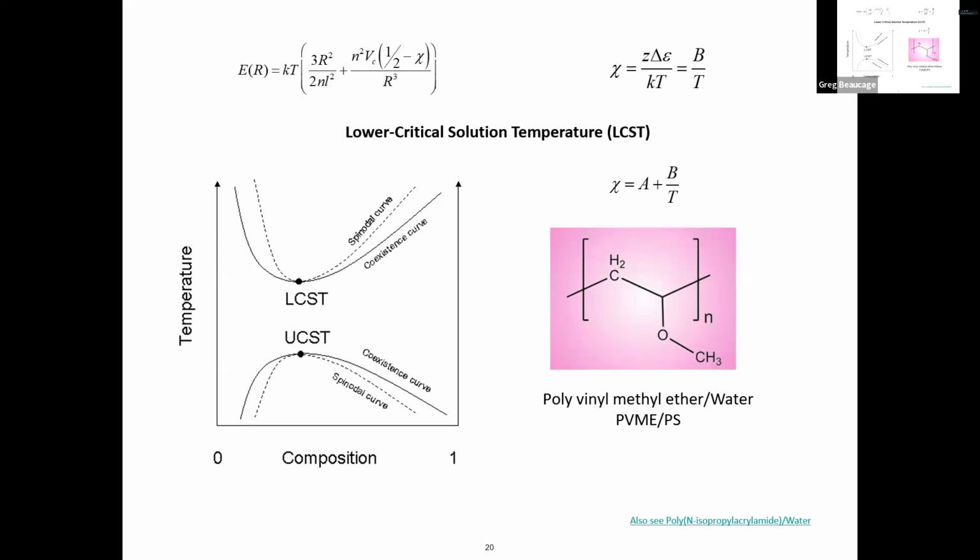And so if you dump this stuff on the table and you try to wipe it up with hot water, that's a bad plan because it just phase separates and makes goo. The hotter you make it, the stickier and gooier it gets. So if you want to clean it up, use ice water, and it goes right into solution. So it's pretty weird. That's the basic way that polymers behave. So anyway, all right, there's that business.